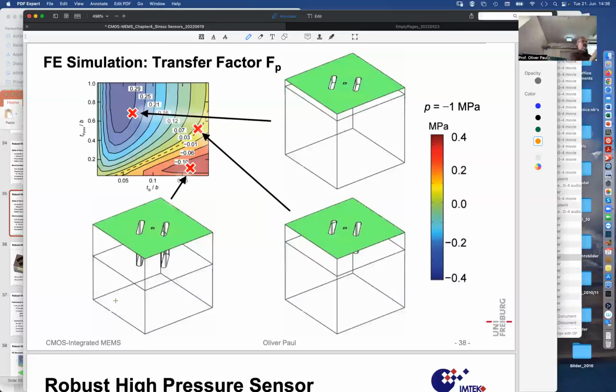It will just bend. And so the silicon bends also, but that means that there is a tensile stress on the surface. It will be expanding. It will not be compressed like in the top right picture. It will now expand. And that means that the sensitivity to an isotropic pressure acting on that structure will be in the opposite direction. Because instead of a compression, the surface experiences an expansion. And so here's a sensitivity factor that has the opposite sign, minus 0.1.